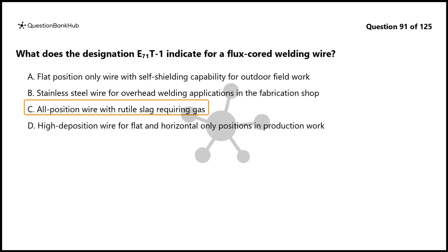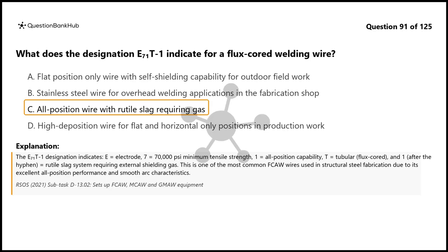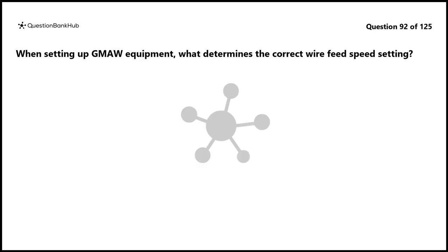The correct answer is C. All-position wire with rutile slag requiring gas. The E71T1 designation indicates E equals electrode, 7 is equal to 70,000 psi minimum tensile strength, 1 equals all-position capability, T equals tubular, flux cored, and the 1 after the hyphen equals rutile slag system requiring external shielding gas. This is one of the most common FCAW wires used in structural steel fabrication due to its excellent all-position performance and smooth arc characteristics.